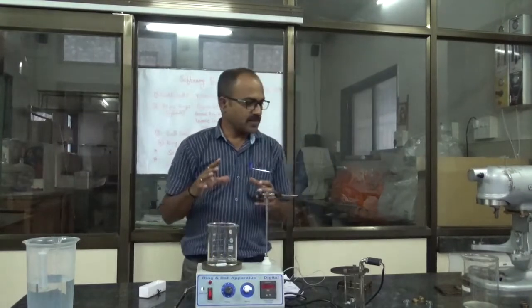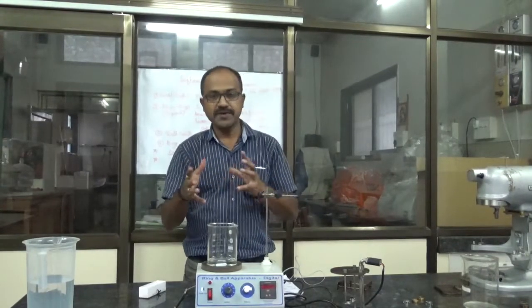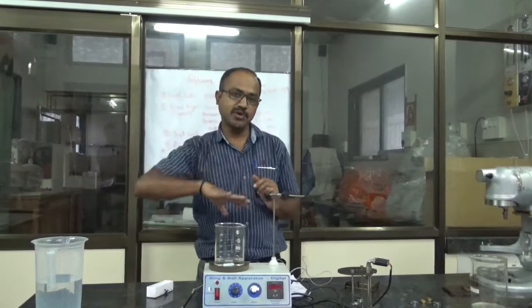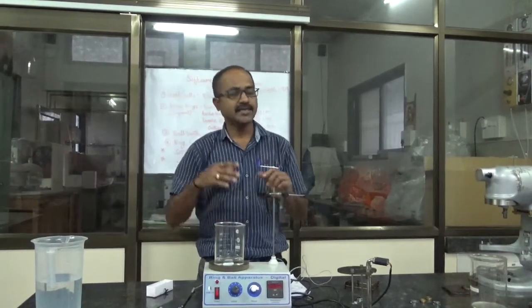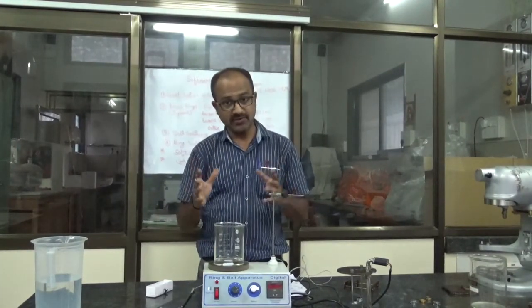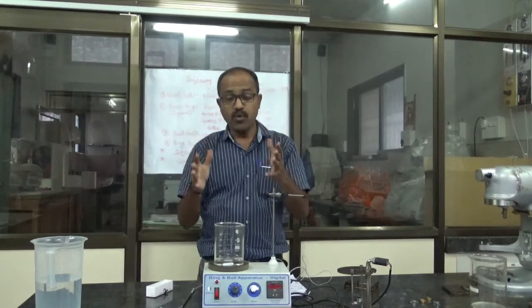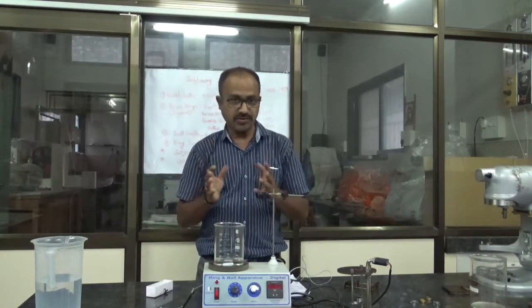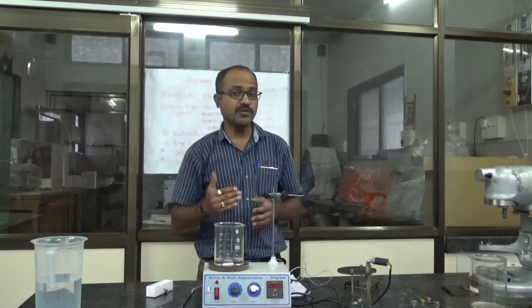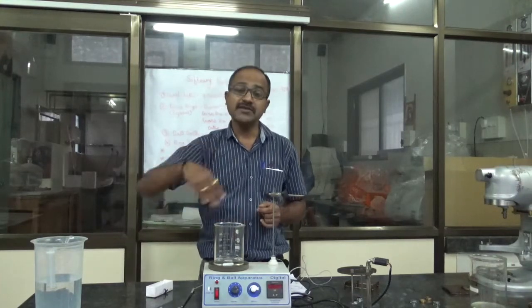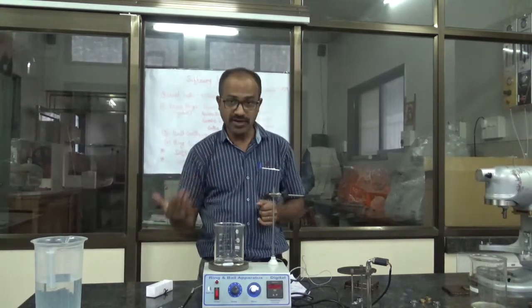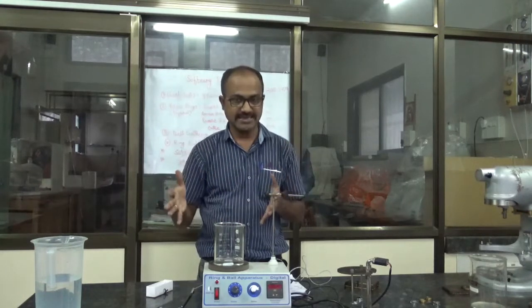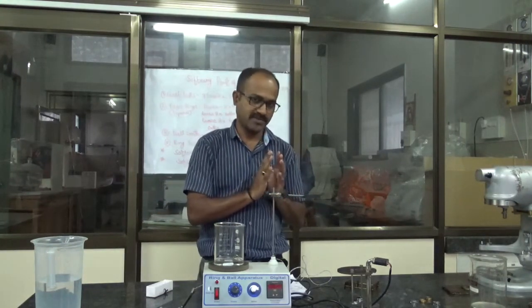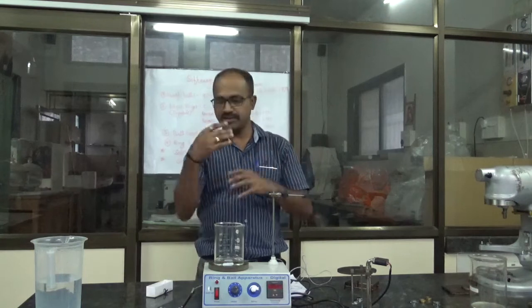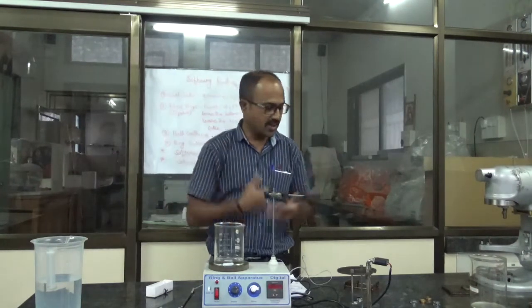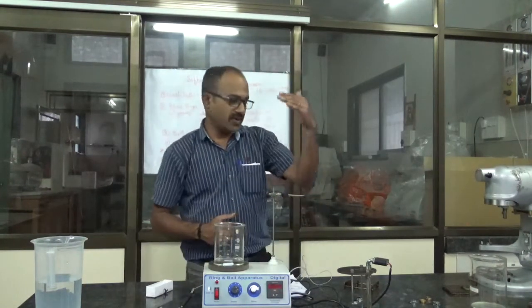Okay, so if the bitumen softening point is below 80 degree centigrade, then you should use distilled water, that is boiled and cooled distilled water. And if my softening point is above 80 degree centigrade, then you should use glycerin instead of water. Okay, so this is the difference when the softening points are different. Now, what is the first step?